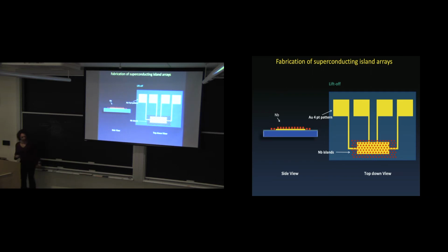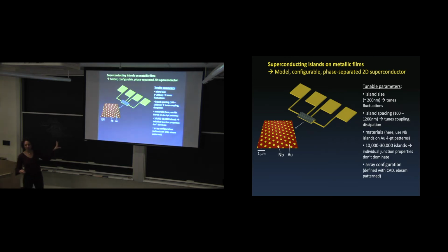It's a long story about why we use niobium, but we can evaporate niobium. It lifts off really nicely. It's why we use it. And also it works above 1 Kelvin, which means we can measure it very quickly. That's how you often choose materials, for convenience. And also we wanted simple materials here for a model system.